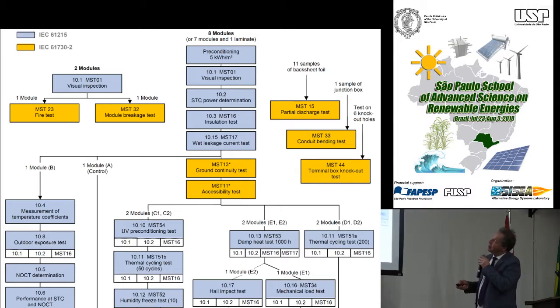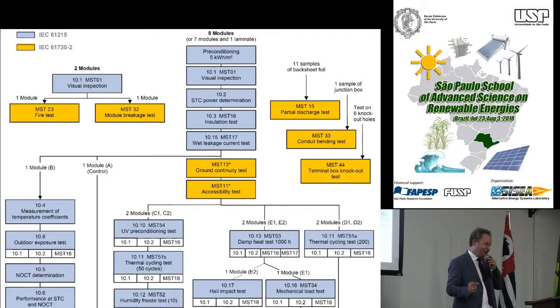There's a module breakage test. That means the modules can break, but the splinters of the glass are not allowed to be bigger than 6.5 square centimeters, so nobody can get hurt if the module breaks. Fire tests. It's a quite expensive test, costs $4,000, but the outcome is always the same. The module doesn't burn, but you have to perform it according to the American norms, which is here the IEC 61730. So you spend $4,000, you know the outcome already in the beginning. It doesn't burn, but you have to perform this fire test in order to succeed.